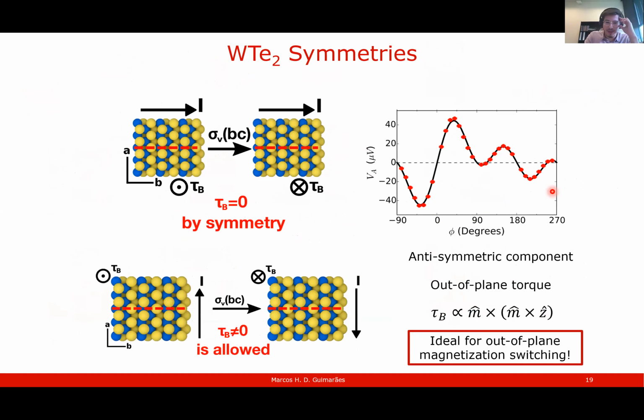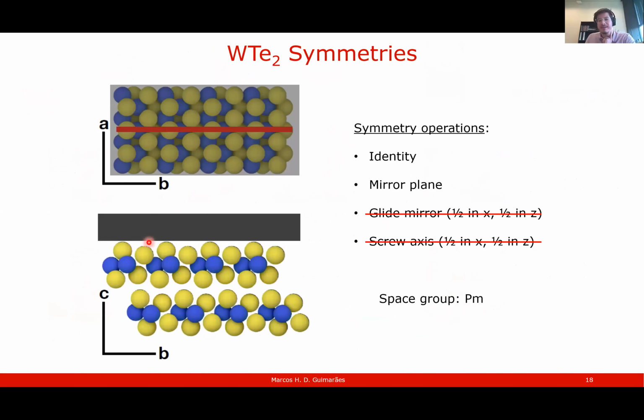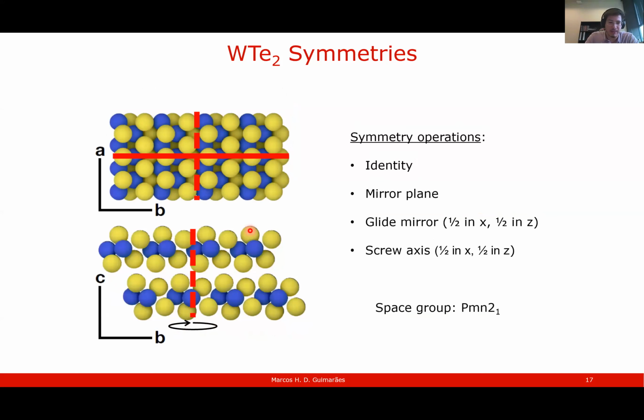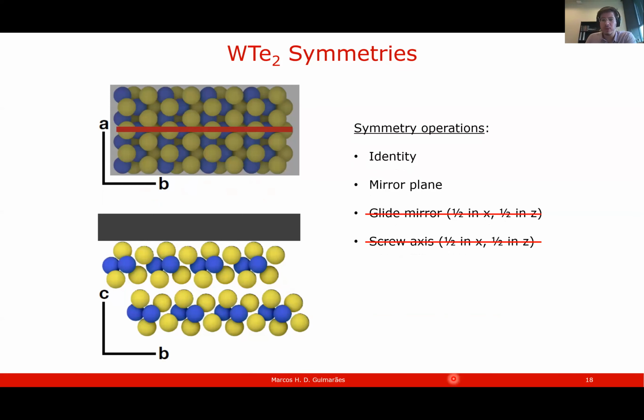I cheated a little bit because in principle, at the interface, these symmetries are already reduced. So in principle, you don't need to have the permalloy there. If you just look at a crystal like that, for example, a bilayer device, then these symmetries will already be small. You already lose the translation in the z direction, just because you have an interface in there. But then you have an effect also at the bottom interface, right? Yeah. Here it is even stronger because you have the substrate on one side and the permalloy on the other.